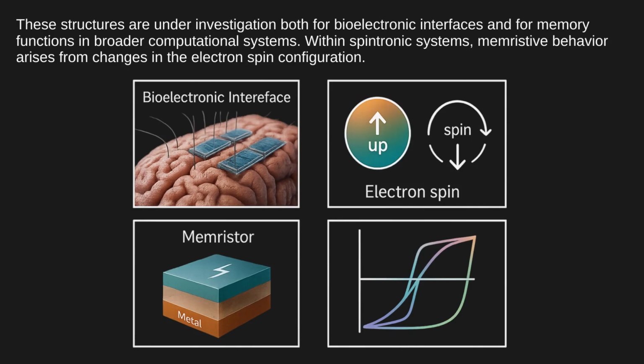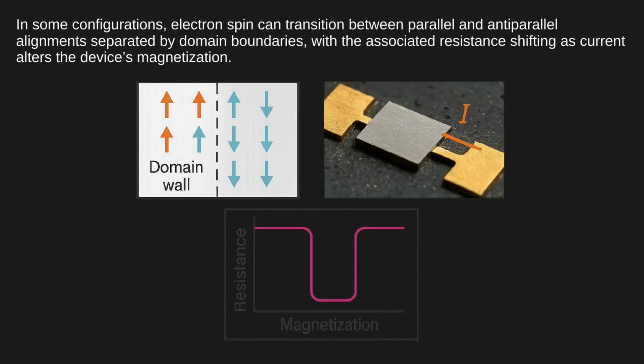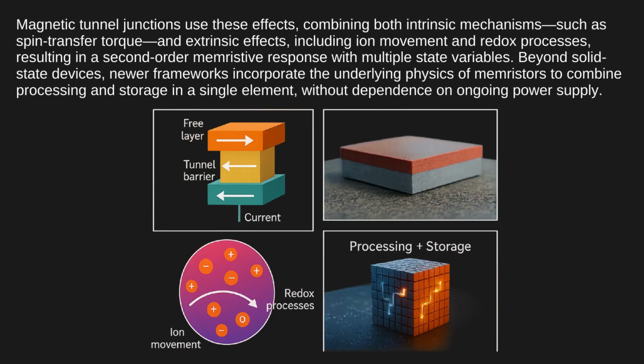Within spintronic systems, memristive behavior arises from changes in the electron spin configuration. In some configurations, electron spin can transition between parallel and anti-parallel alignments separated by domain boundaries, with the associated resistance shifting as current alters the device's magnetization. Magnetic tunnel junctions use these effects, combining both intrinsic mechanisms, such as spin transfer torque, and extrinsic effects, including ion movement and redox processes, resulting in a second-order memristive response with multiple state variables.